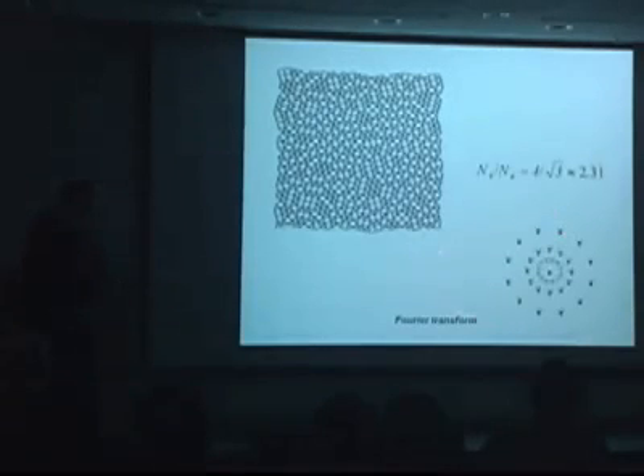But what we have here is the Fourier transform of an infinitely large domain. So in terms of crystallography, it's a perfectly long-range ordered system, a single crystal type pattern, but the structure has no translational symmetry. Another weird thing is that by counting these spots, you can say what rotational order, what symmetry element, you can assign to this structure. It gives you 12 spots, so this lattice nominally has 12-fold rotation. In classical crystallography, it's as forbidden as 5-fold rotation in a crystal. These two things cannot coexist.